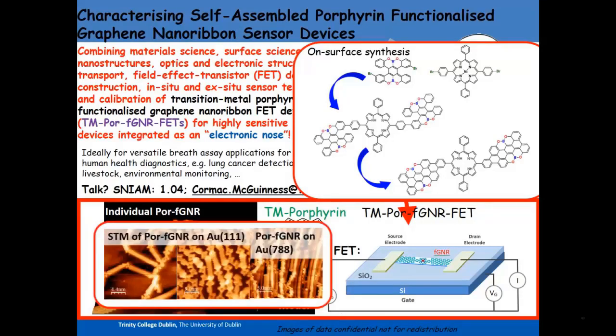So what's next? Here are some other STM images of these porphyrin networks. Porphyrin networks are connected by these graphene nanoribbon wires, and we can do them on surfaces such as Gold(111), which is very flat, and we can get these kind of networks going in all sorts of directions, or we can do these on a stepped surface. So here we have parallel nanoribbons incorporating these porphyrins.